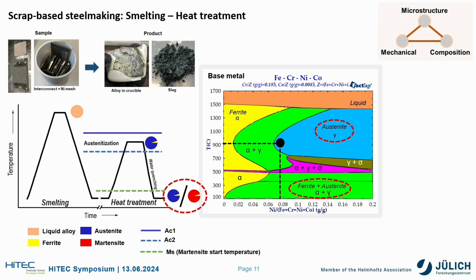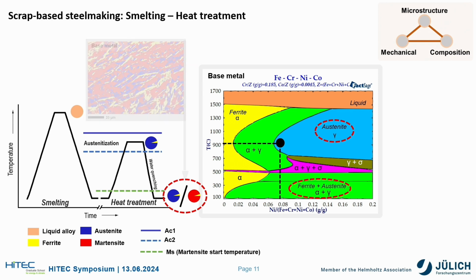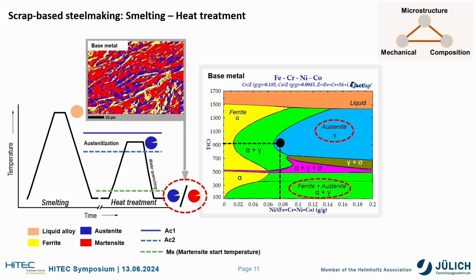First is that the microstructure would follow this equilibrium phase diagram, and we would observe a predominant austenite microstructure with a small amount of ferrite phases. The second thing that could happen is that austenite would transform to martensite via a non-equilibrium diffusionless transformation. And this particularly happens when the alloy is being cooled below its Ms, or the martensite start temperature. So results have shown that the resulting microstructure is predominantly martensitic, as you can see with this red phase map here. And therefore, austenite wasn't prevailing at ambient temperatures.